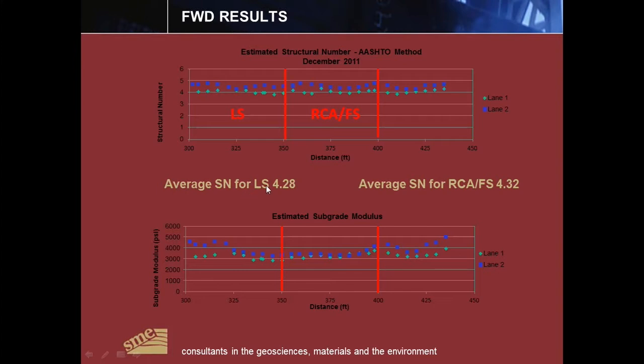The average structural number for the limestone paving test section was 4.28, whereas the average structural number for the recycled concrete aggregate foundry sand blend was 4.32. Rounding these off, you can see that the structural numbers were essentially equivalent. This demonstrates that initially the recycled concrete is working or functioning as a structural part of the paving section as well as the limestone base material.